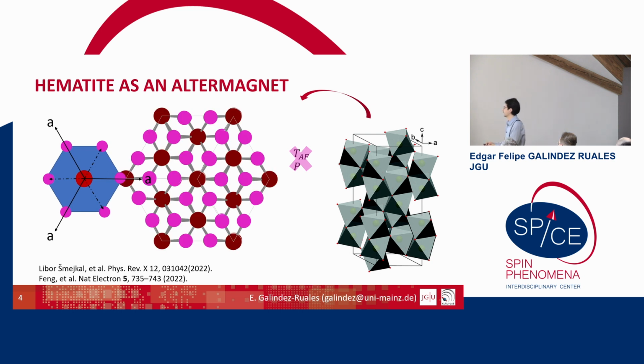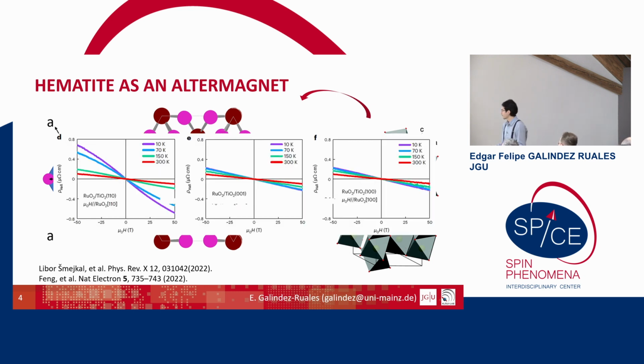We would like to measure the altermagnetic properties of hematite, which is a candidate, but there is a small problem that I mentioned: hematite is insulating. So how do we measure Hall resistivity and a Hall coefficient in an insulating material? This is the case of ruthenium oxide, where they were seeing a rise of the anomalous Hall conductivity, Hall resistance, and Hall conductivity.